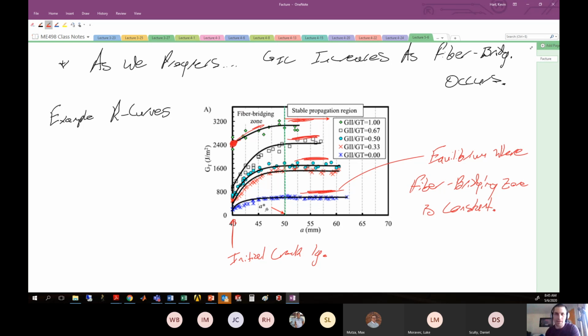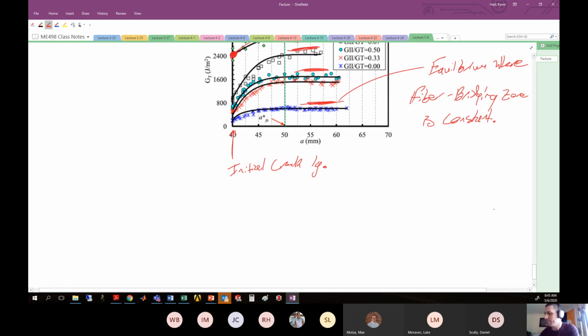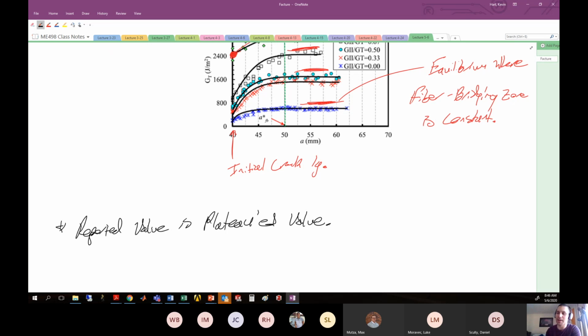So when you see this behavior on an R curve, it starts low and then it increases slightly. That's an indication that you have this significant fiber bridging occurring. So the actual critical strain energy release rate that people will report is kind of an argument. But generally, the reported value is the plateau value. That's because in real life, you wouldn't have this Teflon inside of the piece. You're only using that Teflon to initiate and propagate the crack. So you would have fiber bridging in real life, and therefore you want to see what this plateau value is, because that's representative of the fibers that would hang on in real life. Right?